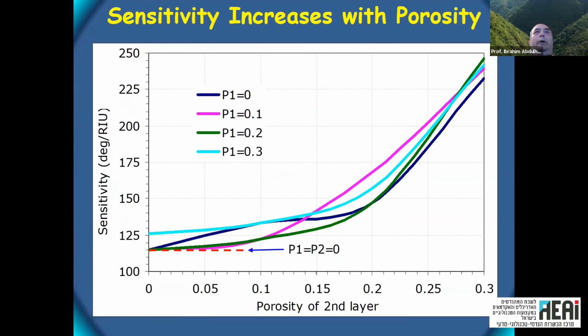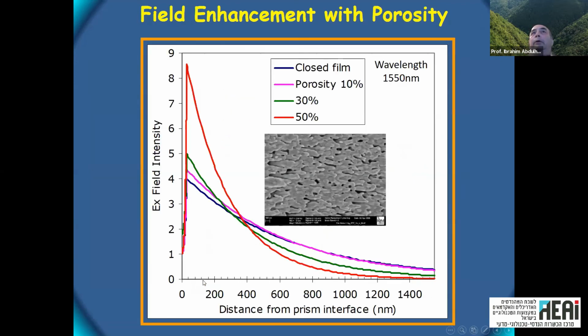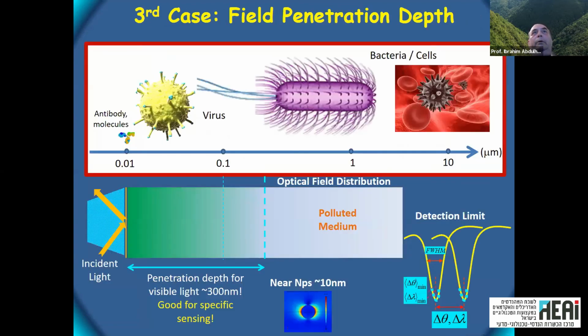So you can easily calculate sensitivity for this composite structure versus porosity, and the simple calculation showed indeed that you can get almost 3 times improvement in the sensitivity if you increase the porosity by 30%. And also the correlation with the field, it shows very nice correlation. As you increase the porosity, you get larger field enhancement. So we proved the concept, and then we wanted to move to something else.